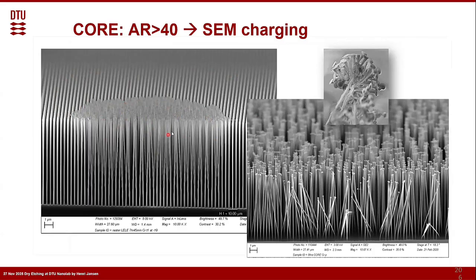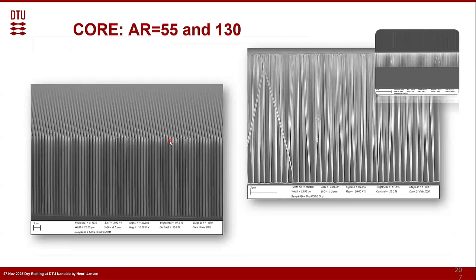So it is caused by how we look at the structures. The closer you look, the stronger this effect is. If you zoom out, it will not happen. It's about how many electrons you bombard on it. So if you don't zoom in, you can see they are nicely straight, and then again go up to extremely high aspect ratios, maybe up to 130, as you can see here.